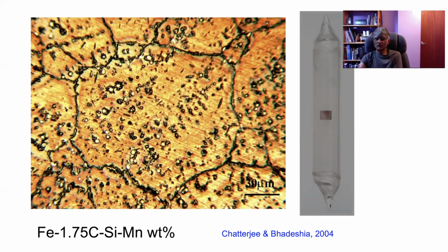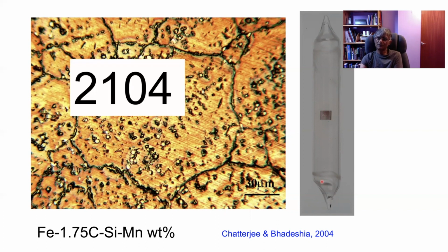Now, this experiment was started in 2004, and a metallographically polished but not etched sample was produced and put inside an inert gas in a sealed silica tube. And there were 2 of these samples. One is located in the Science Museum in London. And in the year 2104, it will be interesting to see if there are surface displacements produced by the formation of this bainite.